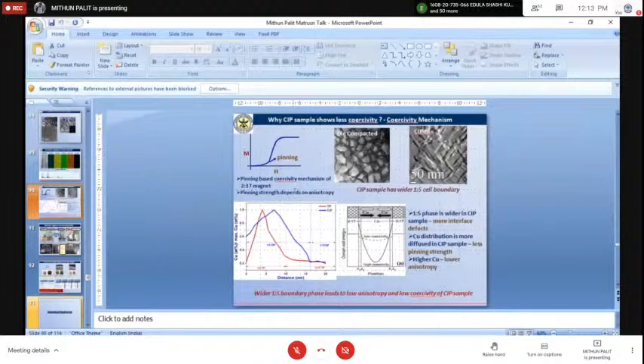So when we see how the anisotropy varies with the copper concentration, we find that the wall anisotropy increases with the copper enrichment. Therefore, when you have the wider width, the pinning field is very diffuse. That means in a wider width, I have a copper gradient from one edge to the center, and it is decreasing, and therefore the pinning is not very efficient. Whereas in the conventionally processed magnet, the precipitate width is very thin, and there you have a very sharp distribution of copper, and the pinning field is very strong.